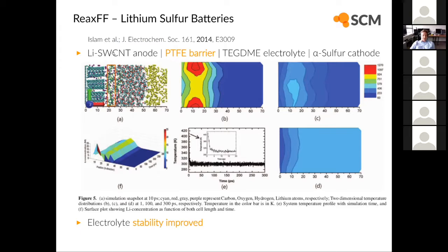these lithium ions. And as these temperature plots then show here again, they are still hot in the beginning, but they stay mostly within the anode material and do not reach into the electrolyte, and therefore, the electrolyte itself stays intact, and that greatly enhances the stability of the electrolyte and thus the whole battery system.